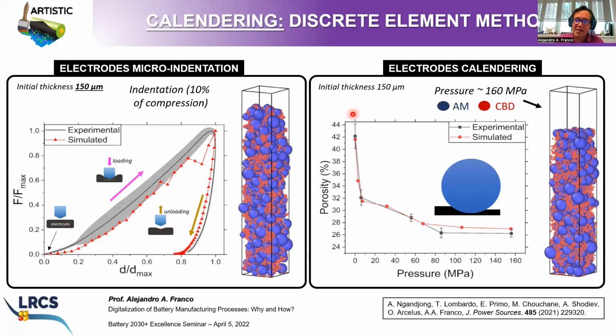And you see here that the model fits very well in terms of porosity that is being calculated upon compression. So the experimental values, okay, of porosity versus applied pressure during the calendering process step. The model is fit also based on microindentation experiments, okay? And that's why the model is capable to capture both plastic and elastic behavior of the electrodes upon calendering process step, right?